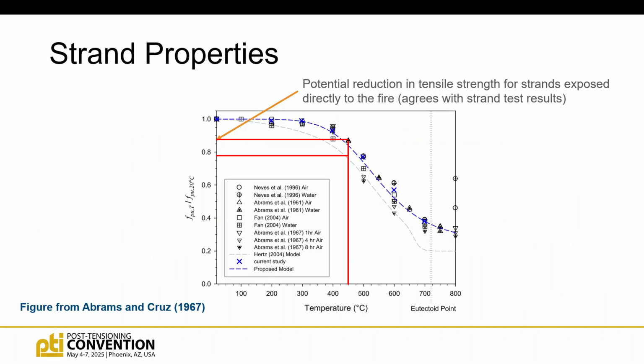And then the other thing we're doing here is now we're trying to look at what degree of relaxation or loss of pretension would occur at some of the levels of temperatures we were finding, which are roughly in this 450 range Celsius. And you can see we're somewhere in there in this range of between a little bit below 0.8 and somewhere around 0.9. So if you take the initial stress in the tendon, you could say, well, we've got a 10% reduction in the force in that tendon due to this relaxation due to the heat. And so that's something now that the designer can work with.